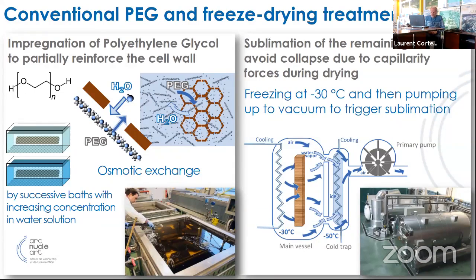So the conventional method used almost everywhere in the world consists of impregnation of polyethylene glycol, said PEG, to reinforce a bit the cell wall, followed by freeze drying. Freeze drying allows drying without liquid phase. It is sublimation and so on without capillarity forces. That's what is done all around the world, and what we do also in our workshop when there are no other concerns.